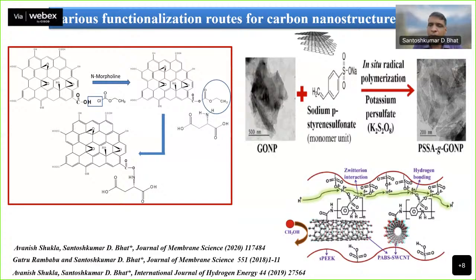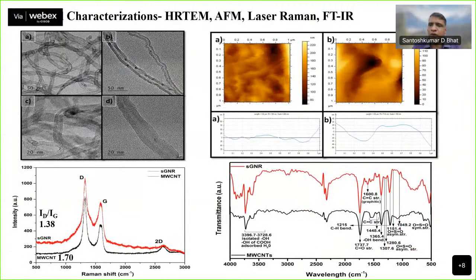So this is what we have been doing. And then there are various ways to characterize it. One is the typical way of seeing the graphene nanostructure change, through high resolution TEM, where we can see the unzipping of carbon nanostructures. We also use Raman, where we can distinguish the various forms of carbon, where we can see the D band, G band, 2D ratio. Then we can work on various defect forms of carbon also.